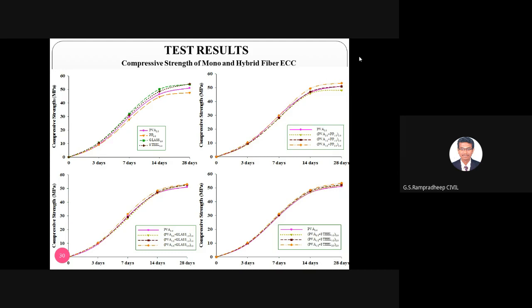All the concretes, from PVA to PVA, PP, glass and steel, have attained the compressive strength, right? As I already pointed out, compressive strength will come, but we have to focus mainly on the bending, flexure and direct tensile strength. For the grouping, the pink color is PVA 2%. If I am clubbing PVA plus PP at 2%, it is showing the maximum result, right? PVA plus PP is showing the maximum result.